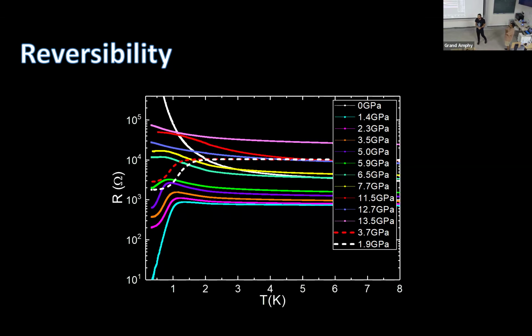You never get back to the blue curve or the white curve. No, the white curve is in the ambient when I open my diamond anvil. Unfortunately, this is why it's also very hard, because when we cross the point where it's flexible, when we try to open the gasket, the medium inside just jumps, and our indium oxide sample, part of it remains on one anvil, part of it jumps to the other diamond, and we have this abnormal sample. So it's really hard to say what's going back to the amorphous when we go to the ambient pressure.